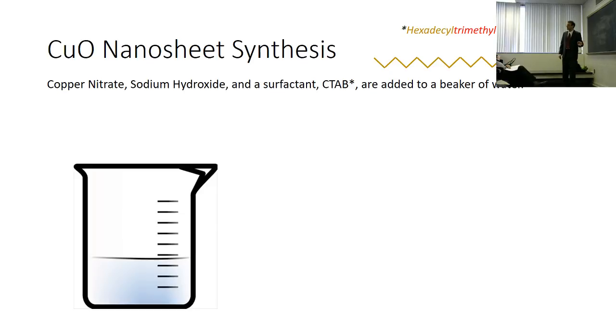To make copper oxide nanosheets isn't actually that hard. What you need first is a copper source, so I use copper nitrate in water, a base, sodium hydroxide, and a surfactant, CTAB. Surfactant, that's soap. It's got a hydrophobic end and a hydrophilic end. That's why it's really good as soap. It takes off grease because grease is hydrophobic and water is hydrophilic, so it just comes right off. We use this here for a different purpose.